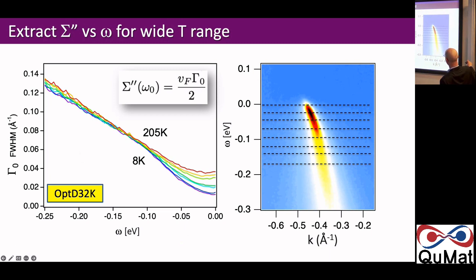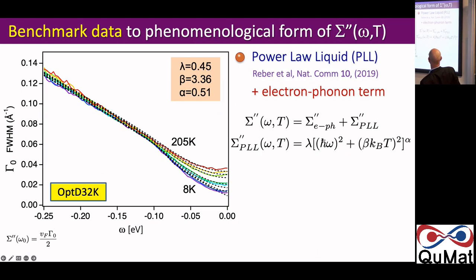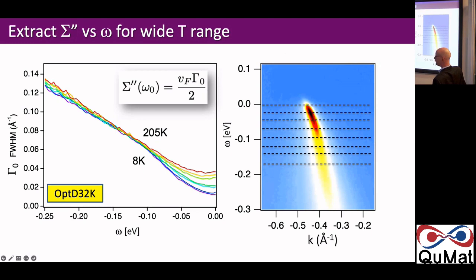So if you do this at these different frequencies, you will get such a curve. So this is now the full width half maximum of this distribution. So half of this would be the thing related to the self-energy. And it's as a function of frequency, because we can start at the Fermi level and move up to higher binding energy. And then we do it at different temperatures, and they're color-coded. I don't show all of them because it would get too busy. So this is just the experimental data.